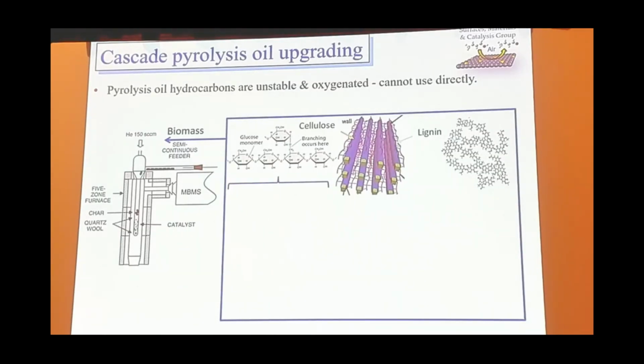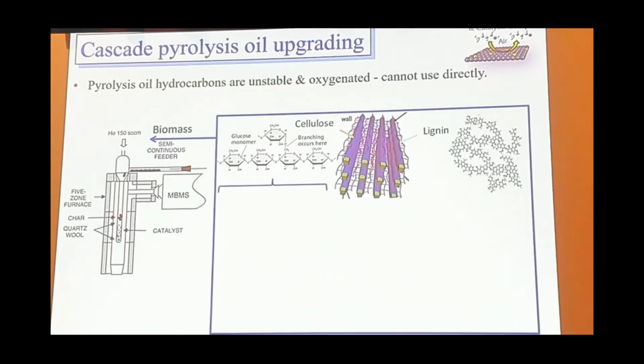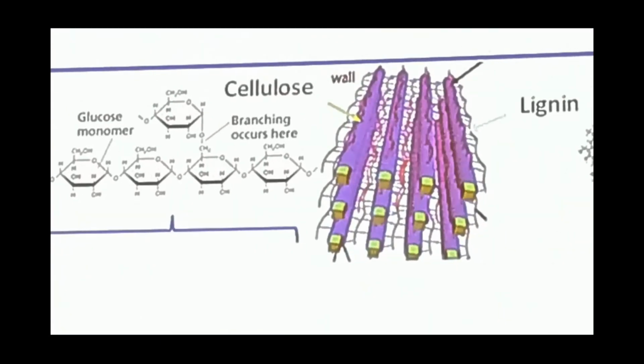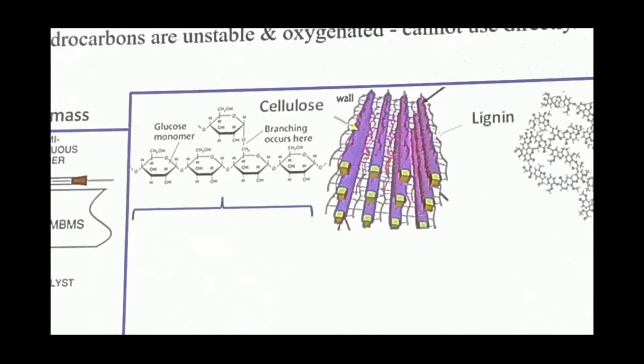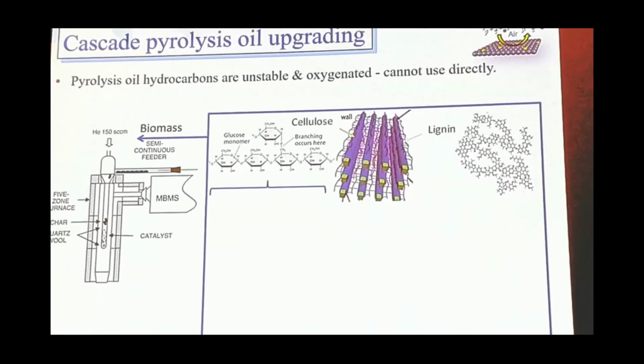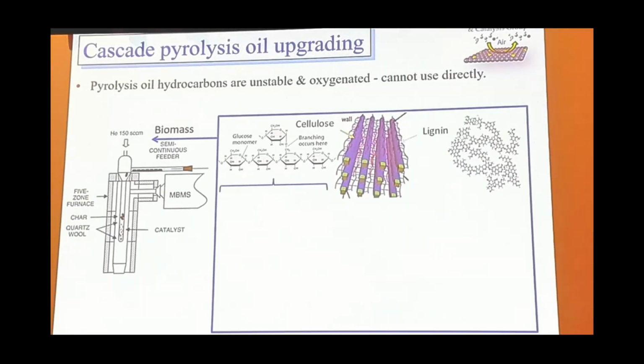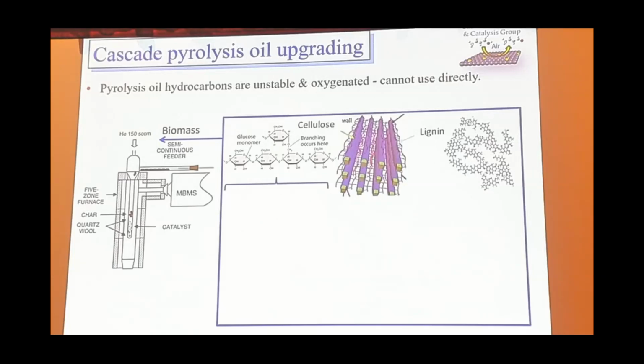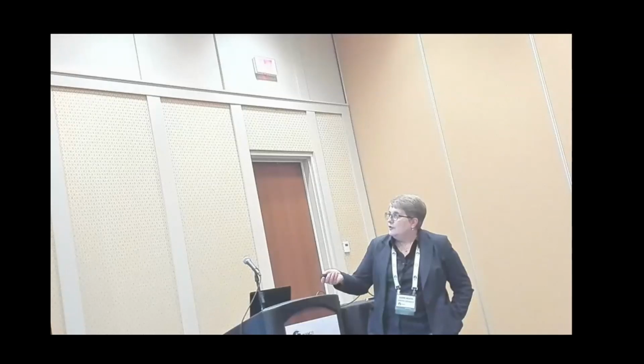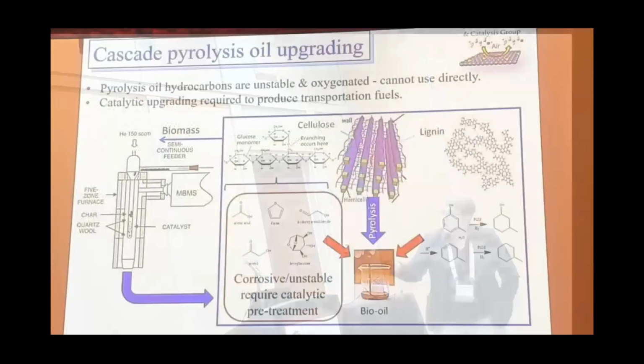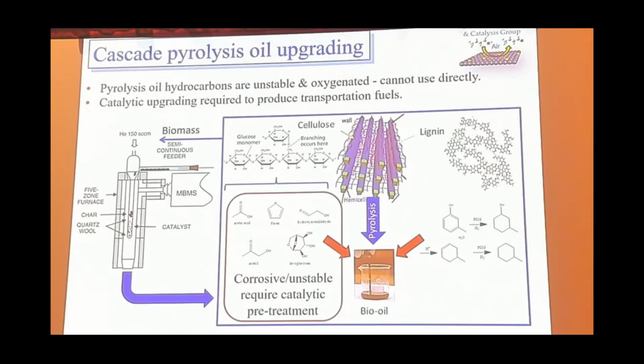Okay, so I'm going to change tack a little bit now and talk about pyrolysis oil upgrading. And again, here we have different cascades that we can look at in terms of trying to stabilize pyrolysis oils, improve yields before you have to start to go and hydrotreat. So essentially you're taking your biomass, you heat this up under an inert atmosphere, typically 400 to 500 degrees. You'll end up with a bio-oil. That bio-oil is horrible, sticky like tar.